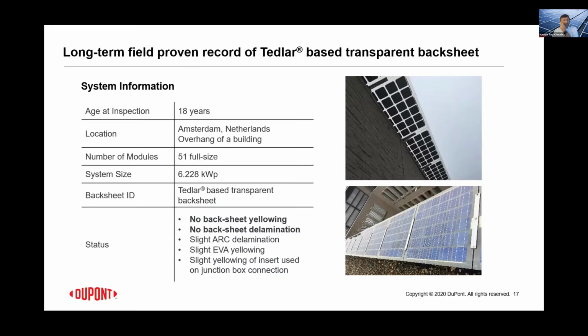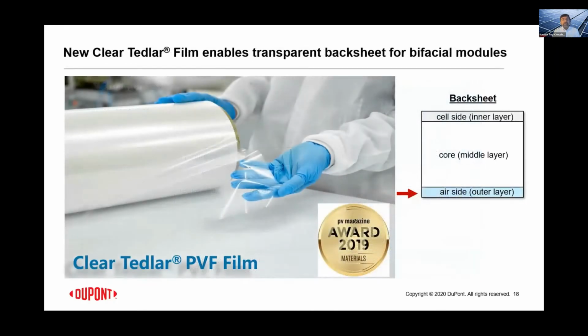So armed with that information, we improved upon the formulation and the package that goes in the film that enables the newer generation of transparent backsheets. So this is enabled by the clear Tedlar film. I'm showing here a cross section of the backsheet and pointing out that the Tedlar film actually goes on the outer layer of this backsheet structure, and it performs a very important role of protecting all the inner layers from the ravages of weather for hopefully 25 to 30 years.